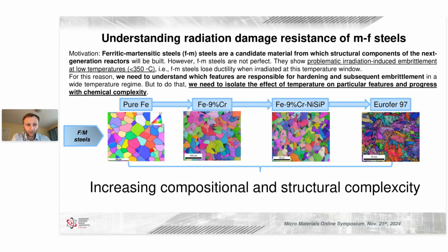And to do that, we decided to go a few steps back and produce model materials containing only iron with 9% chromium, and the system with addition of solute atoms. By conducting the same tests, both irradiation and high temperature, on each of these four materials, we are able to isolate features which are responsible for the hardening effect.